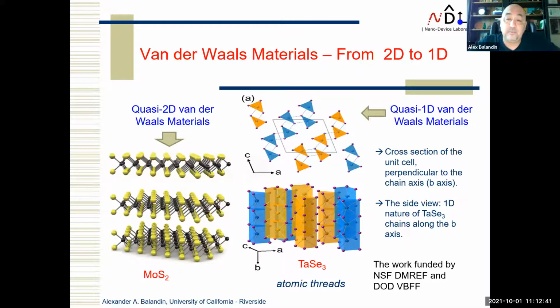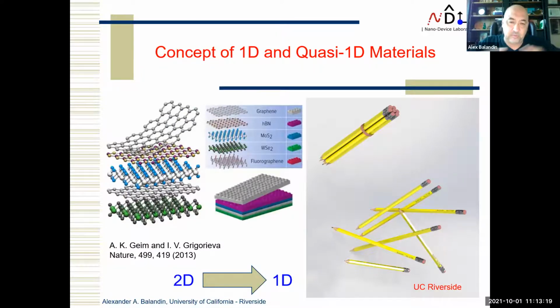However, you can also think about another group of materials. Examples of them are transition metal trichalcogenides, and they have strong covalent bonds in one direction, but in perpendicular planes they may have van der Waals bonds or weaker covalent bonds. And in this case, you can break down these materials into atomic chains, or bundles of atomic chains, which would be needle-like. This is essentially also a van der Waals material, but it has a distinctly different geometry. So this is what I call quasi one-dimensional material. And that's the concept that we have been developing for some time.